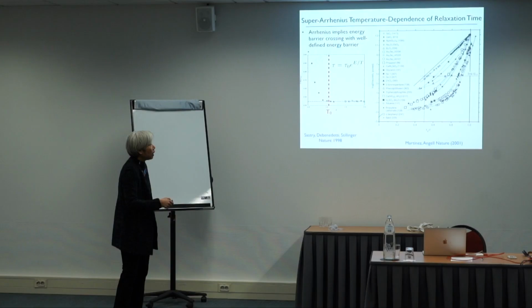And there are some systems where it's sort of straight. Those are network glass formers like silica, like what's in window glass or something like that, or the glass vessels I showed you. But a lot of glasses are not like that. They are very, very curved on this. That's a super Arrhenius behavior, that the lower the temperature is, as you go this way, the relaxation time just shoots up much faster than linearly. So that's a super Arrhenius behavior.